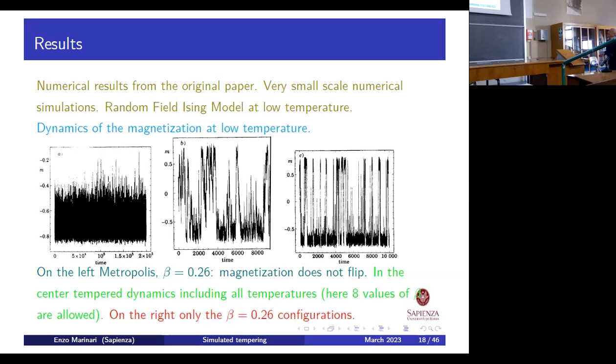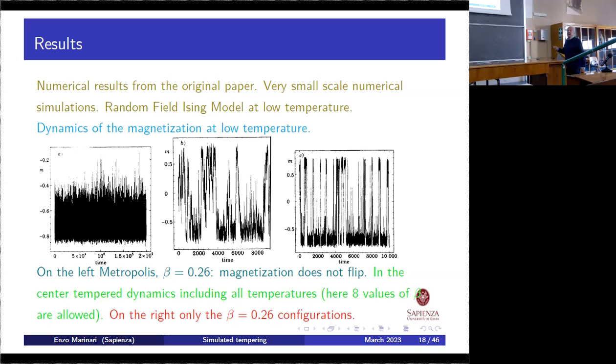These are figures from the original paper. They seem very naive now, as everything we did 30 or 40 years ago seems now, but still, right? I show you, this is Monte Carlo time. This is a picture of the magnetization in the system with usual Monte Carlo. This is the random field Ising model that was our quite simple model to study it. And this is the evolution of the magnetization, right? At beta equal 0.26 with usual Monte Carlo. There is a state, and there is an opposite state that you know, because the Hamiltonian is symmetric under inversion of all spins.